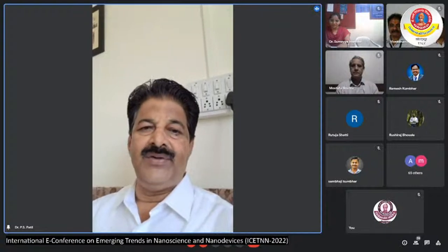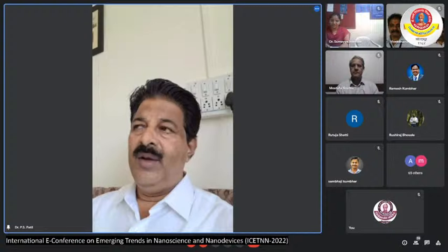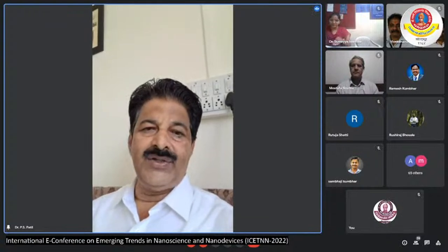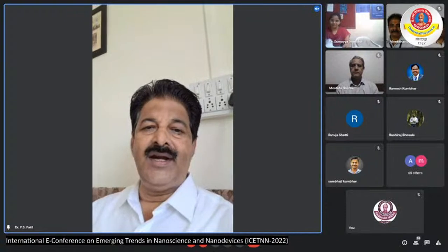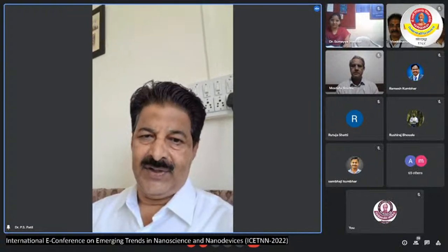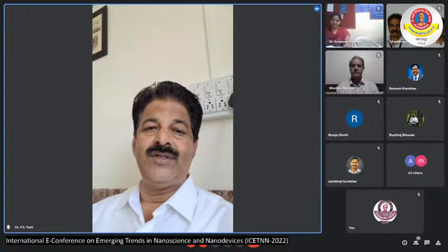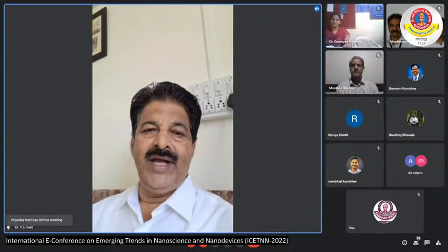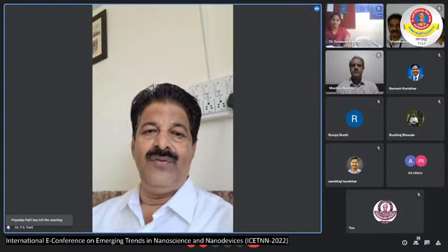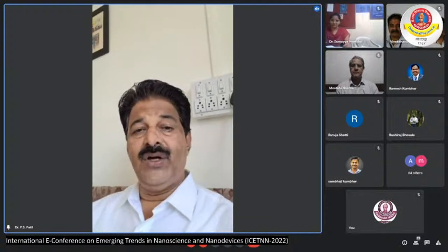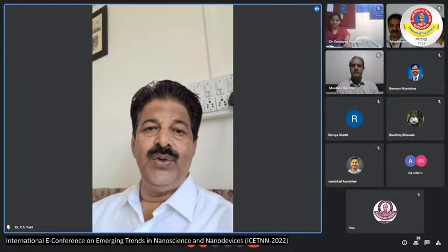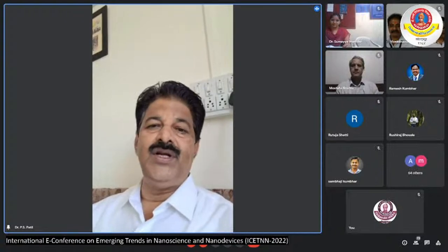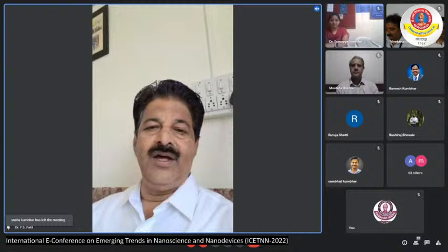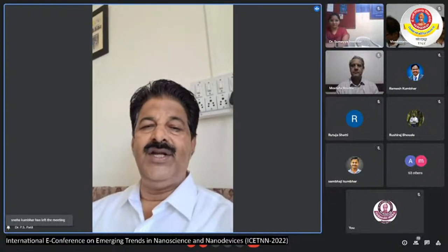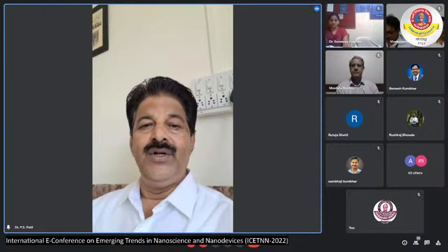For example, if I have tungsten oxide, it is transparent. But if I apply the voltage, H plus or lithium plus ions start intercalating into the tungsten oxide host lattice. And therefore, the composition of the tungsten oxide changes from WO3 to HxWO3. X is the amount of H plus ions which are intercalated into the tungsten oxide host matrix. And because of the conversion of tungsten oxide into HxWO3, the change in color is exhibited. So change in color is only because of intercalation of H ions or lithium ions into tungsten oxide.